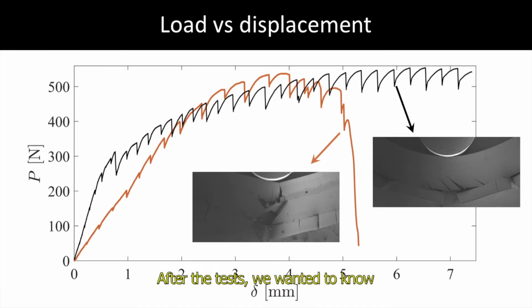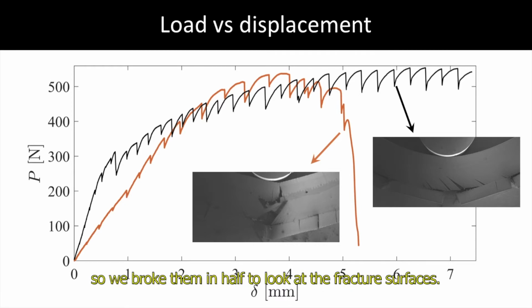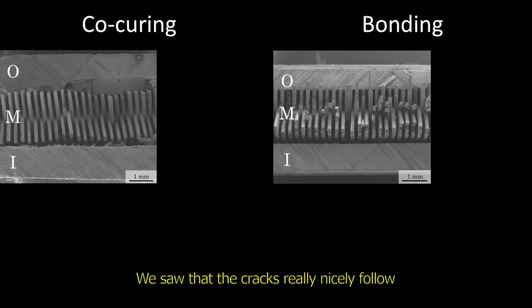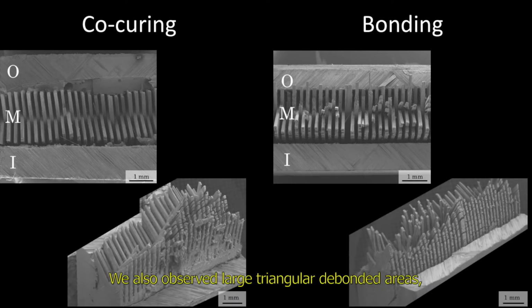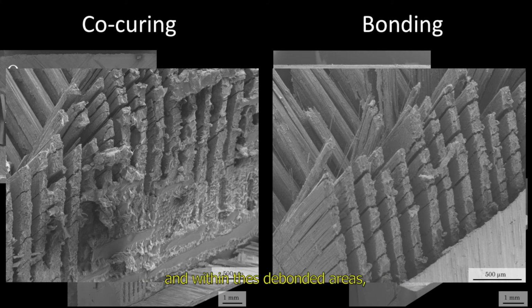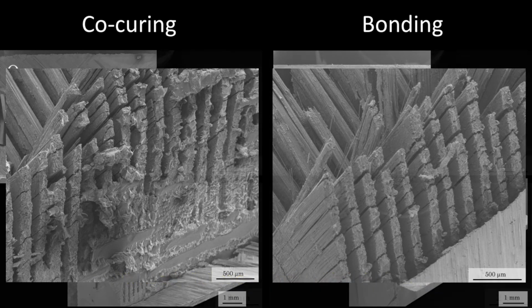After the tests, we wanted to know what kind of damage there is in the specimens, so we broke them in half to look at the fracture surfaces. We saw that the cracks really nicely follow the ±45-degree orientation in the middle layer. We also observed large triangular debonded areas, and within these debonded areas, we saw regular arrays of splits along the fiber direction. These are all signs of extensive diffuse damage.